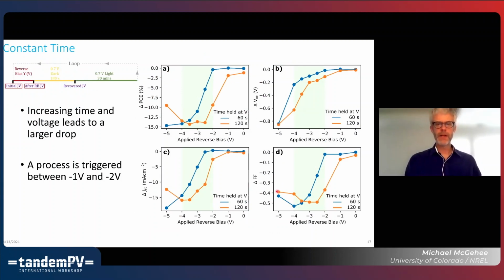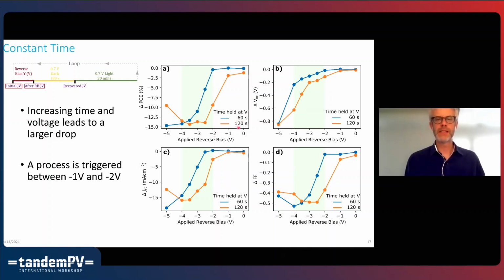Here you see a summary of more data. The x-axis is the applied reverse bias. The blue curve is when we had that bias for just 1 minute, and orange is just 2 minutes. And you see that maybe not a whole lot happens within -2 volts, but once you go past -2 volts, the degradation is really pretty severe. I mean, this is over 10% loss in just 1 or 2 minutes. Altogether, the degradation is about 100,000 times faster than it is under 1 sun at the maximum power point.